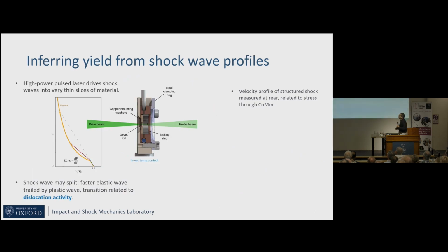And to do that, we had a very talented group of students who then excise small amounts of material. These aren't necessarily PMMA, but this is a classic experiment where you would take very thin slices of material, and instead of using a gas gun, we want to look at the very first instances of relaxation, very first instances of compression. And so we make the material as thin as possible. We strike it on one side with a laser, and being very careful, we make sure that we test the material in a regime where you'll get an elastic response and a plastic response.